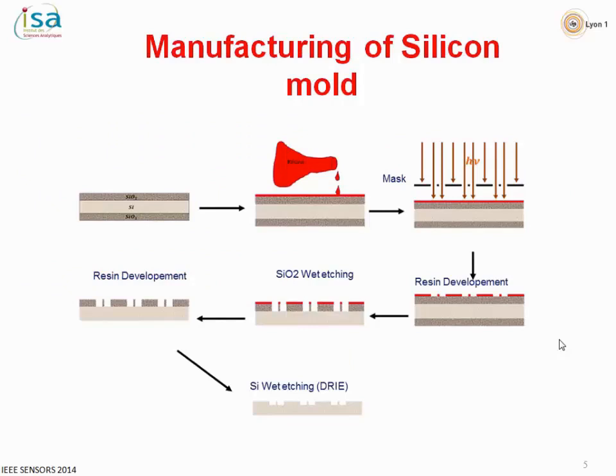First of all, to produce the stamp, we need the master based on silicon technology. This is easy, and the process is the standard way. We grow the silicon oxide, we put here the resist, and we expose it through the mask to UV. After that we develop the resin, we etch the first layer, and after that we do reactive ion etching in order to create our structures: channels, loops, pillars, and so on. And after that we remove the silicon oxide.